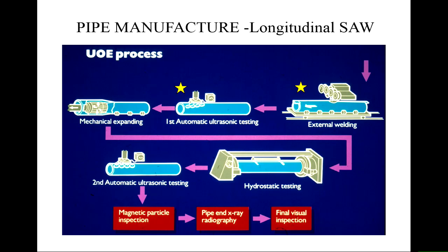If you want to get pipes to match up perfectly, they have to go through this expansion process to be perfectly circular at the end of it. And it also enables you to fit into the hydro testing machine, so you pressurize it with water to make sure it will withstand the rated pressure. So each pipe segment that is produced is hydro tested, so that they can guarantee that the pipe will withstand the operating pressure and be therefore of the grade that is required.